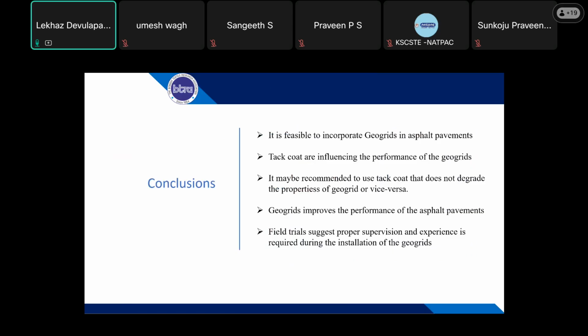When it comes to conclusions, I can say, of course, it's feasible to incorporate geogrid in asphalt pavements, and the tack coat is playing an influencing role in the geogrids. The rate of tack coat depends upon the grid; different grids require a different dosage of tack coat. We also found that RS1 tack coat may remove the bituminous coating on the grid, so we need to check that further. We want to check with different types of tack coat whether the tack coat itself is degrading or the aggregates are puncturing the grid, by our installation damage test.